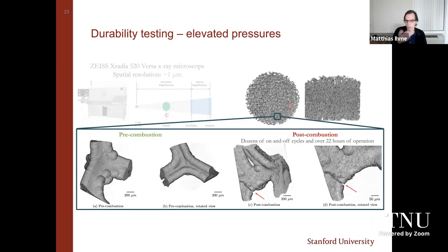So what we have taken here is some pre-manufactured porous ceramic structures, and if you observe them during the combustion process, we are essentially seeing that we are forming cracks. These are micro-CT images at a spatial resolution of about 1 micrometer. Pre-combustion systems look very homogeneous, very well structured. If you operate this for about 22 hours, which is a typical operating cycle, we're essentially seeing the formation of cracks inside this porous media burner and also some surface oxidation. And this is a limitation of these porous media burners, since we're using off-the-shelf designs and we currently have very limited control over the material properties.